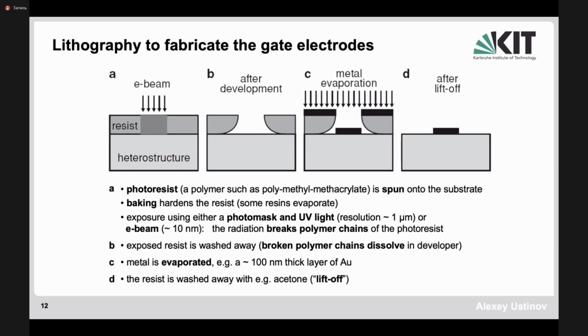And electrons modify the bonds in the polymeric material of the resist. And then once you put this material into the developer, the area where the resist was irradiated is removed. And basically here you have a line which forms a kind of gap between two pieces of polymer, which can be as small as the width of your electron beam. And typically in electron lithography, lines of the order of, let's say, 20 nanometers are possible.